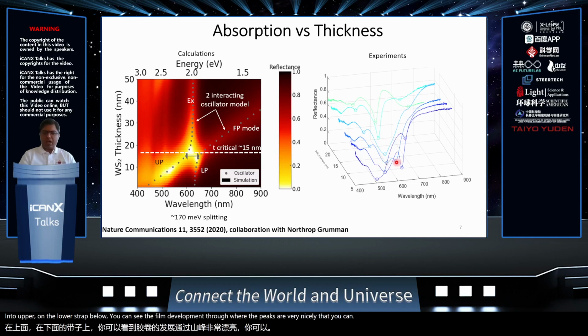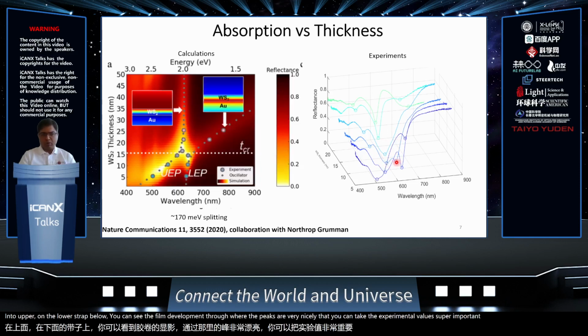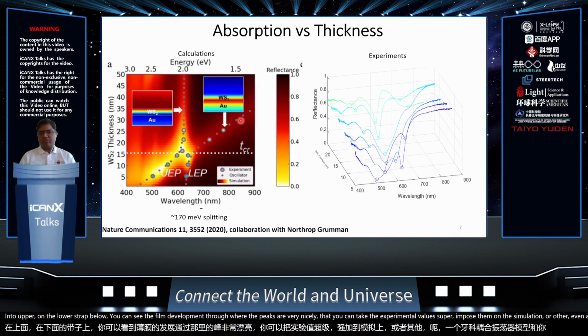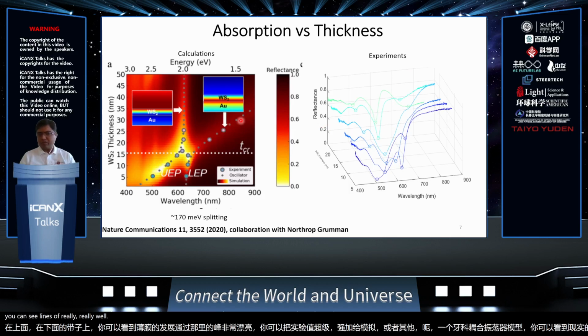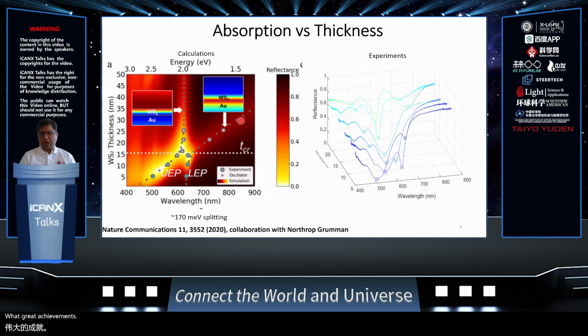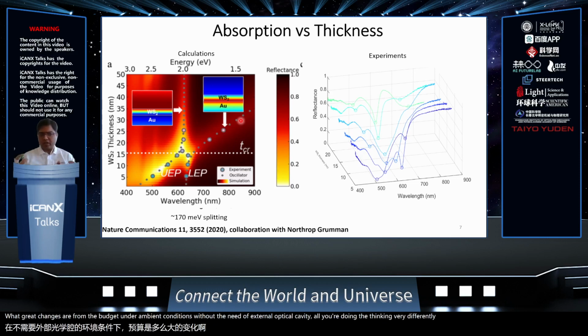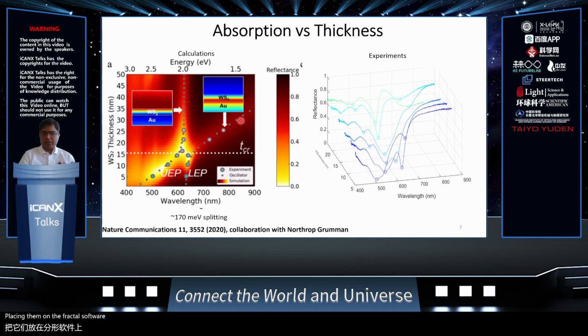You can take the experimental values, superimpose them on the simulations or even a two-coupled oscillator model, and you can see it lines up really, really well. So this was great. You could achieve this at room temperature under ambient condition without the need of external optical cavities. All you are doing is taking very thin materials, placing them on reflective substrates, achieving even near unity absorption in the process. As you can see over here, the reflectance has dipped to 0.